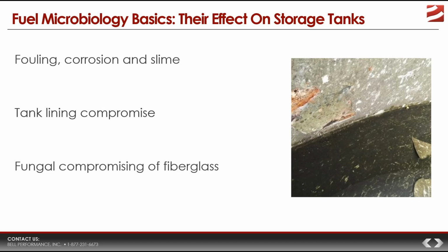Let's say you have a scenario where you get a pinhole leak, a pinhole compromise of the surface. Well, a pinhole is plenty big enough for lots of things to happen. What happens is that fungus actually gets into that pinhole and then goes up underneath the lining. At the same time, you also have moisture that will go into the pinhole and then up underneath the lining. Now, as temperatures change, the moisture will expand and contract, and that will start to compromise or delaminate the lining from the tank shell. And eventually you have blistering, you can have peeling, and so that's non-corrosive damage.